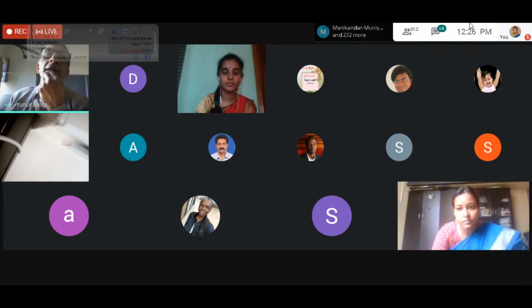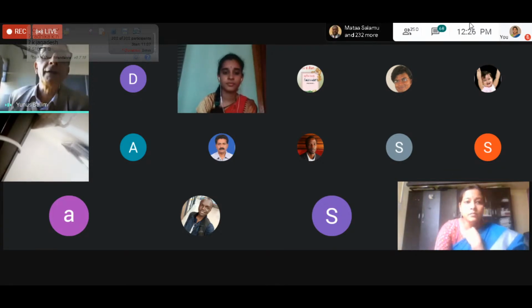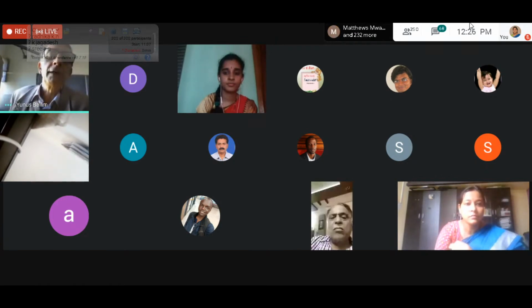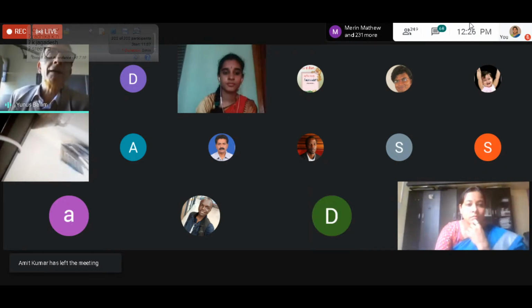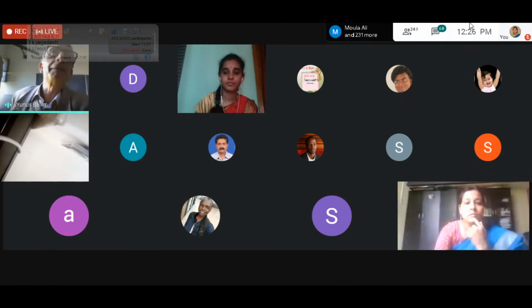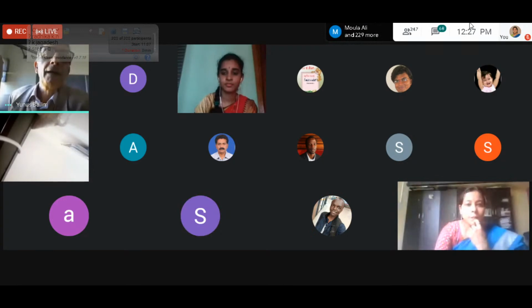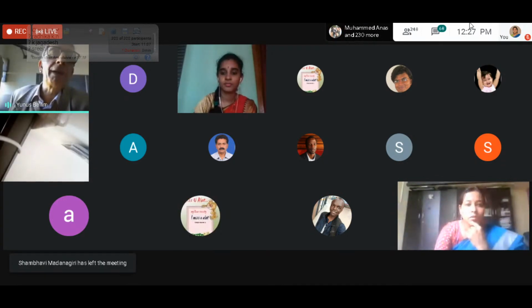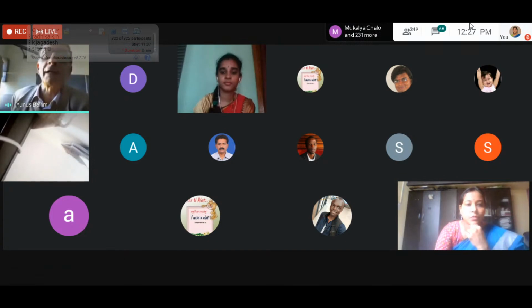And that's important. Let me say that the model that I showed you was used by Professor Manu Santanam at IIT and Professor Ravindra Gettu, with whom I have a research relationship. Manu used my model for a large foundation that was cast in, I think, Chennai. One of the comments about the model is that it tends to under-predict the peak temperatures. Bear in mind that we're using South African cements, whereas in India they were using very different cements with very different characteristics.